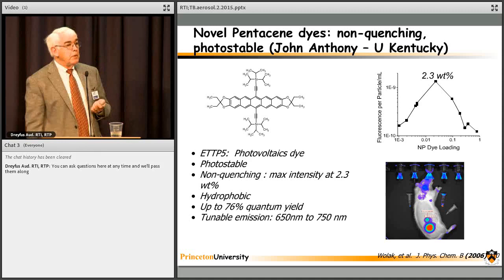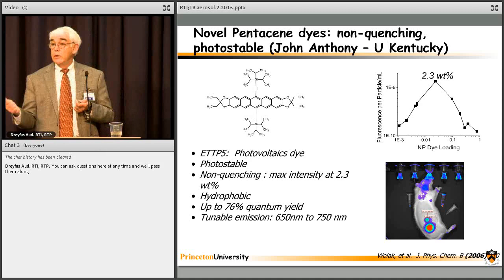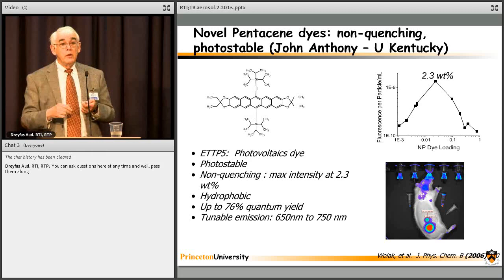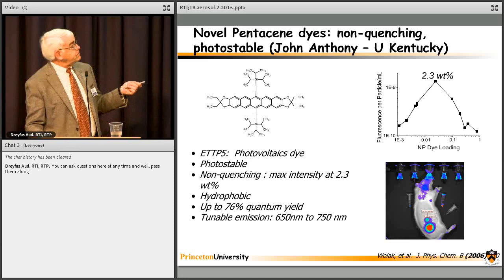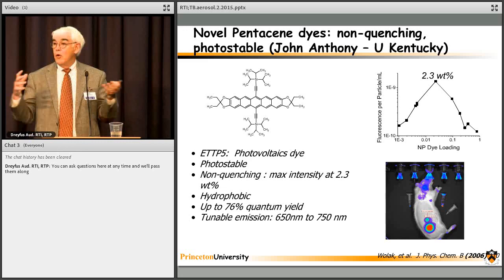And so what do we want for biological imaging? We want something that doesn't photobleach, and we want something really hydrophobic. On a roof solar panel, you want something hydrophobic. It doesn't wash off. Most biologists don't want hydrophobic things. They want things that will wash off. So these are perfect for us. They're extremely hydrophobic. They're very photostable at this version of it. The next longer wavelength is not so photostable, but these are very photostable.